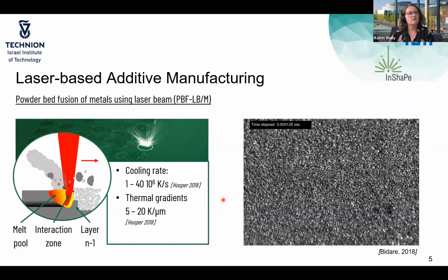And what is changing there is that the energy distribution from the middle to the outer ring is changed. And at the end, we get some kind of donut-shaped rim profile, which means that the intensity of the energy you bring into your process is more in the outer ring than in the middle with this like Gaussian beam profile you see here. So this was the starting point.